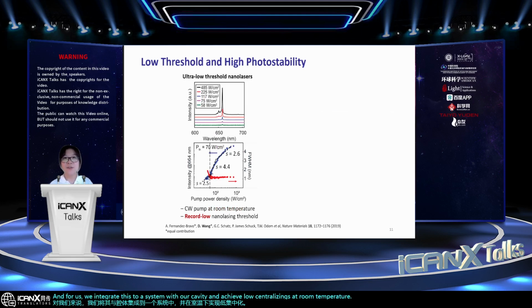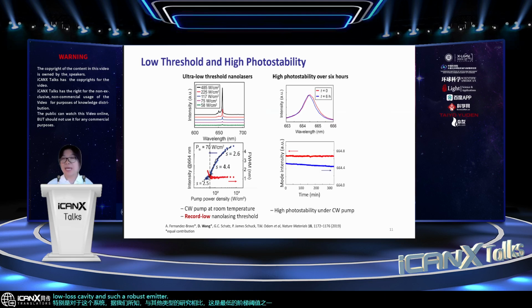What you see here is that under this continuous wave pump, we see a pretty low lasing threshold, and the lasing emission peak is defined by the cavities underneath. Especially for this system, to our knowledge, this is one of the lowest lasing thresholds compared to nanoscale lasers in other types of research. And this benefits from both such a low-loss cavity and such a robust emitter from rare earth-based elements. Such a device is also pretty stable over 6 hours of operation. What you see here is almost no change in the lasing emission intensity and the peak position.